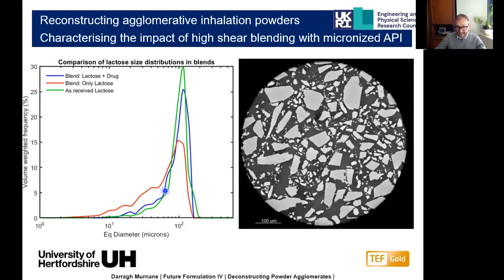So what we're seeing from this three-dimensional reconstruction and pulling out the particle size distributions is that the fine particle drug seems to be protecting the lactose, the bulk lactose, from the fracture that happens during the high shear blending. Of course, this is one experiment. We are intending to look at this much farther, but with the labs shut down at the moment, we're not able to get back into the labs to study this phenomenon an awful lot more.